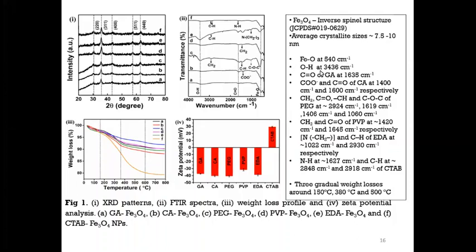If there is ethylene glycol functionalization, or a functionalization where OH groups are present, we can get the water peak at 3436, around 3500. And if there are carboxyl groups, then C double bond O can be observed at 1635. Then you have N-H bending or stretching vibration. N-H bending is around 1627, and C-H stretching vibrations are observed at around 2848 and 2918 centimeter inverse.